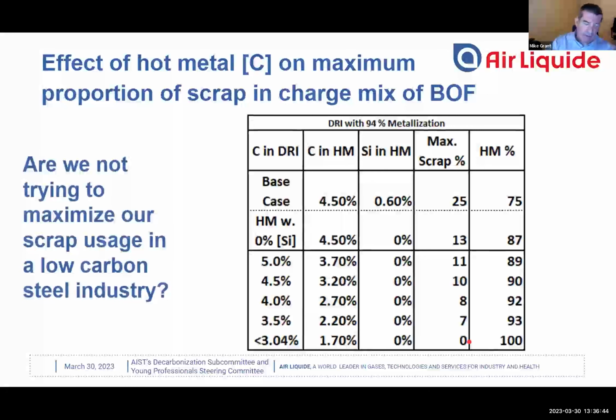ratio down to 10%. And finally, at 3% carbon in the DRI, we will not have enough chemical energy remaining to melt any scrap. And increasing the scrap ratio is one of the key strategies for reducing CO2 emissions. So we got a problem here, and of course it all boils down to how we get this carbon in the hot metal.